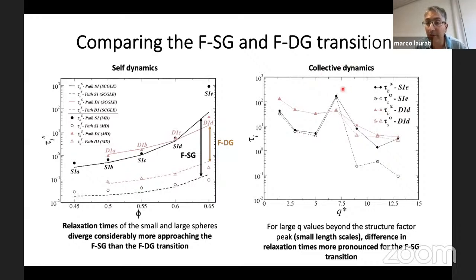But there is also a difference in the collective dynamics, which is revealed in this case by the Q dependence. You can see that at small Q values there is the coupling, which is also, of course, related to the variation of the structure factor of the system. But at large Q values, where we explore small length scales, which correspond for the small particles to the free volume inside the glassy matrix of the large particles in the single glass, we can see, even in the collective dynamics, a more pronounced decoupling in the fluid to single glass than in the fluid to double glass transition.